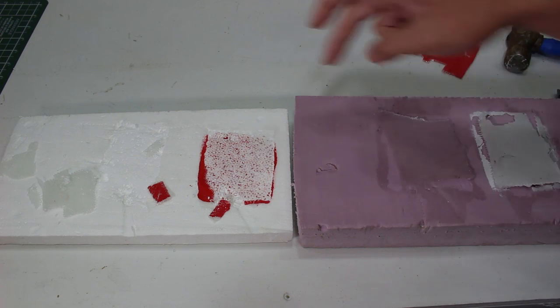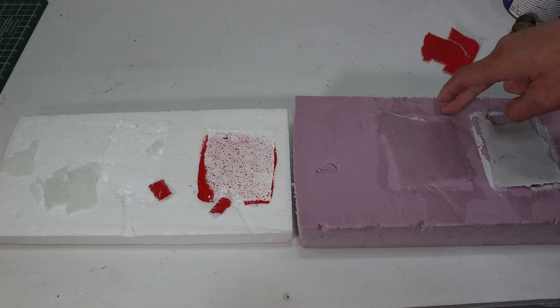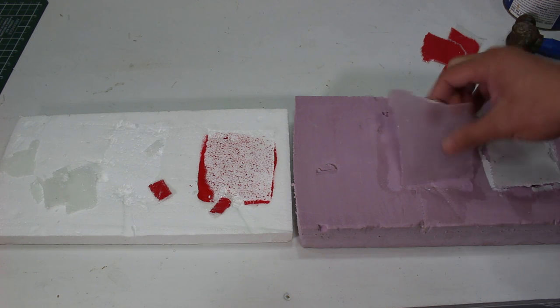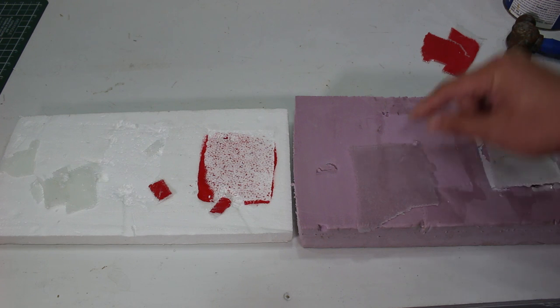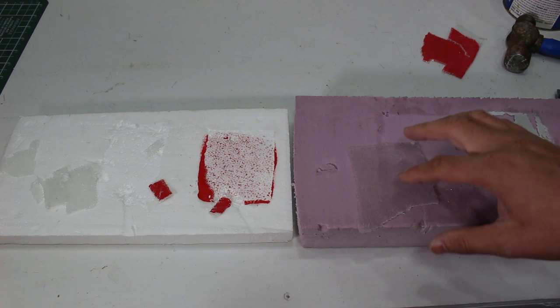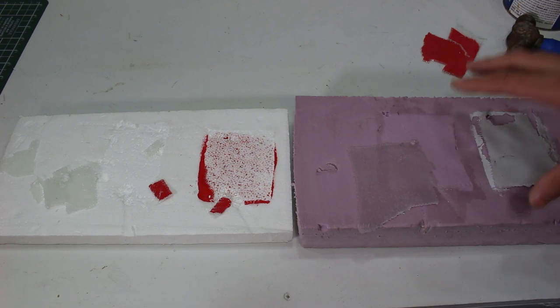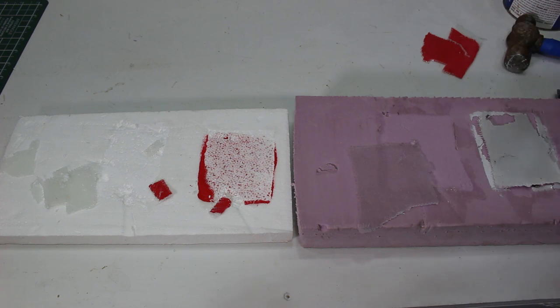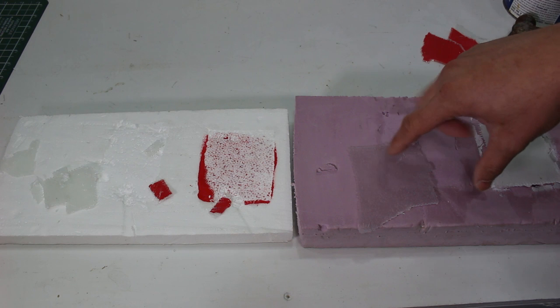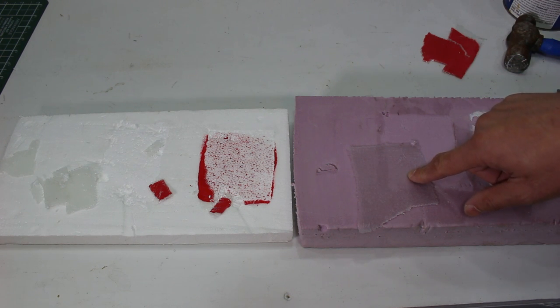So ideally, you probably would want to make your boards out of this. You could get away with making it out of this stuff here, the XPS. But just keep in mind that it's not going to have as good of a bond. So you might have to glass your whole board a little bit heavier. So maybe do a regular glassing schedule, except for around the fins where I just mentioned, maybe glass it with like a 6-6 or something instead of a 6-4. Go with maybe an additional hot coat or gloss coat.